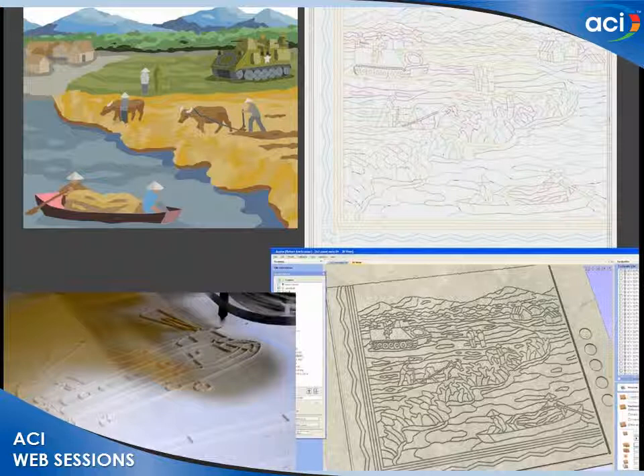From that artwork, once we had the artwork approved, we then used, this time, software. We had less than half of the time for our production that Earley Studios had, so we couldn't use the plaster slab method. It just didn't have time. So we used the software and the computer to not only create the mosaic drawing, but then we used CAM, computer-aided machining software, to create the lines and use that to machine the mold directly, so we didn't have to go through a multi-step casting process, and then a CNC router to machine the ridges that are coming up out of the face of our mold.